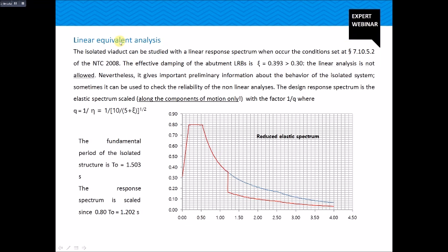The isolated viaduct can be studied with the linear response spectrum when the conditions set at paragraph 7.10.5.2 of the NTC 2008, the Italian standards, occur. The effective damping of the abutment is equal to 39%, that is larger than 30%. For this reason, the linear analysis is not allowed. Nevertheless, it gives important preliminary information about the behavior of the isolated system, and it can sometimes be used to check the reliability of the nonlinear analysis.